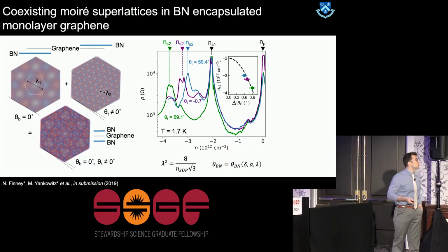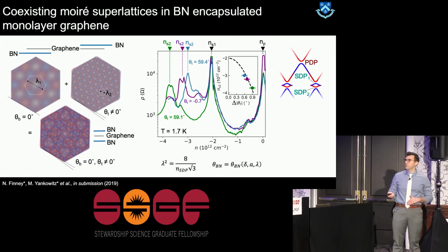Now I basically have two gaps down in the hole band for the graphene. But they're pretty close to each other in energy. And so I'm actually taking two forbidden energy zones and squeezing them together. And so one potential thing that could be happening here is we could be creating what's called a flat band condition, where I have a resistance peak from the first moire and a resistance peak from the second moire. And they're squeezing together to flatten this low mobility band in the middle.